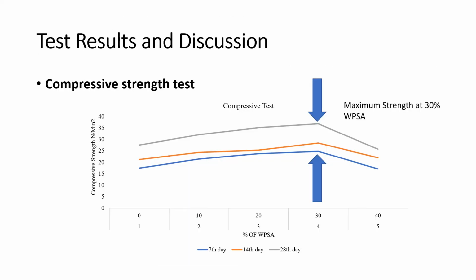So here what you see is the graphical representation of the compressive strength. As you can see, when we increase the percentage of the waste paper ash, the strength basically increases on 7 days, 14 days, and 28 days. That continues increasing up to 30%. But when we increase the percentage of the ash further, then the compressive strength declines.